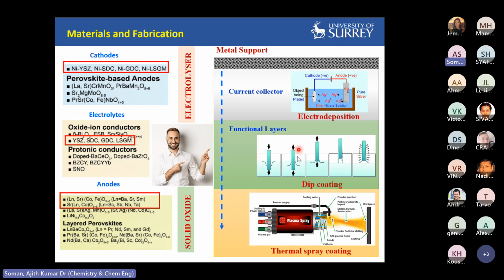Now of course, many research people are working on developing current collectors. We are one among them. So we are working on these materials. We selected the top materials like nickel YSZ and nickel ceria based composite as a cathode, because it has been reported as a high performance cathodic material for water electrolysis. And for the electrolyte we chose the YSZ based, which is cost effective, and we are applying this as an electron blocking layer. And we are mainly developing the cerium based electrolyte, a strong ionic conducting material.